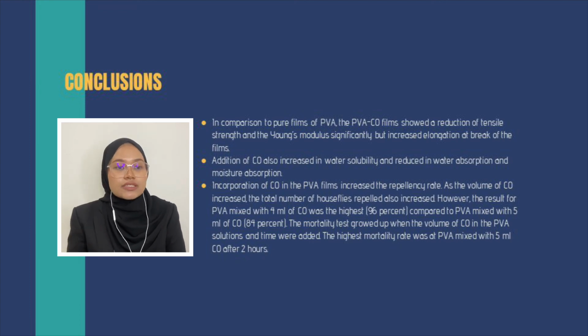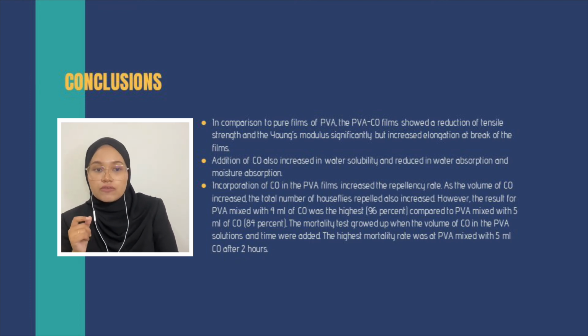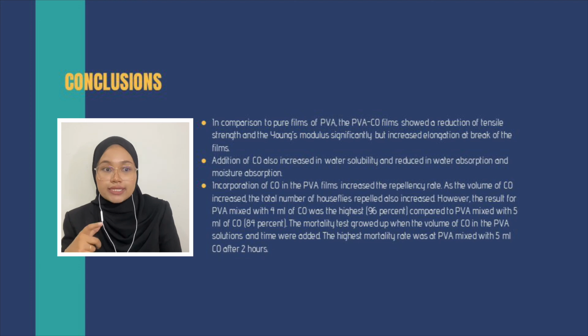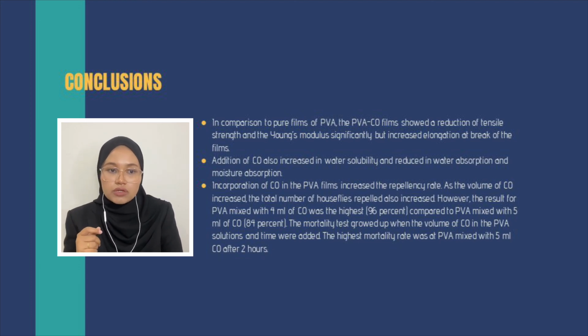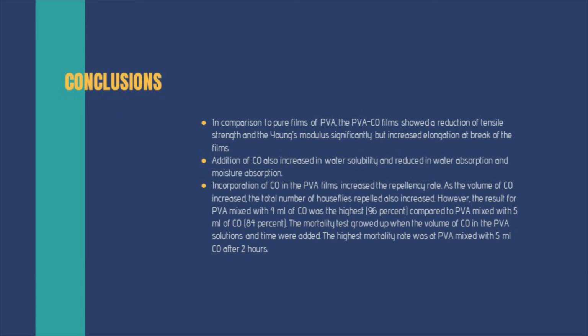The mortality rate grew when the volume of CO in the PVA solution and the time were increased. The highest mortality rate was at PVA mixed with 5 ml CO after 2 hours.